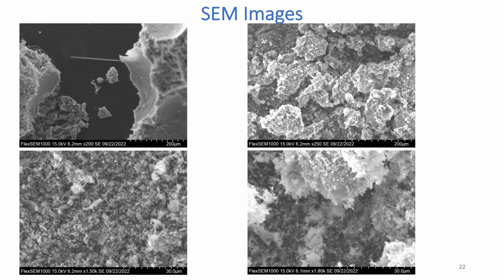We also did scanning electron microscope images of dehydrated gypsum wallboard versus newer drywall, and we found that there is a significant amount of local irregularities within the drywall, but we did find that the SEM approach is a potential method of evaluating the drywall that's been dehydrated.